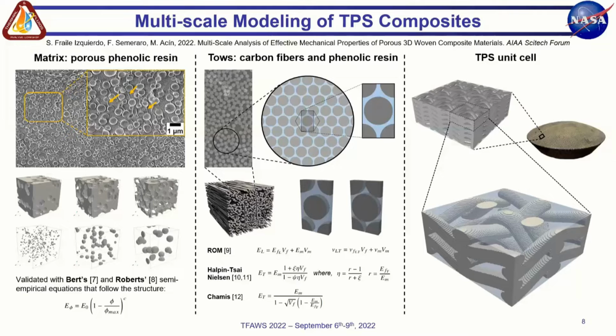In the center, we can observe the modeling of TPS with different packing ratios, or volume ratio of fibers versus phenolic resin. And there are also some equations we can use to validate some of the mechanical properties of the TPS, specifically the rule of mixtures and the Halpin-Tsai, Nielsen, and Chamis equations. And on the right, we can observe the representation of the unit cell that we are trying to model.